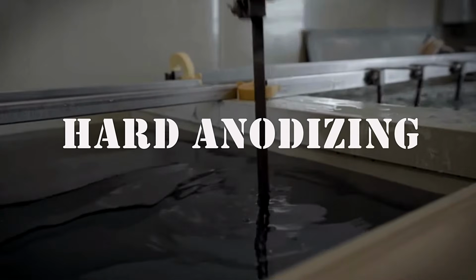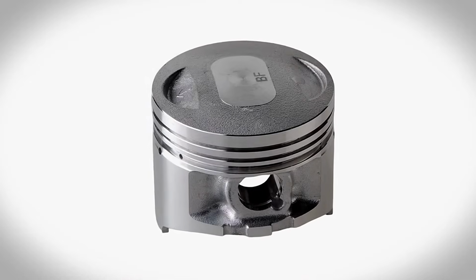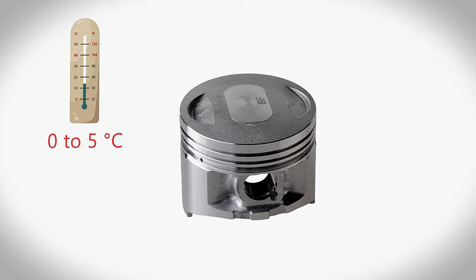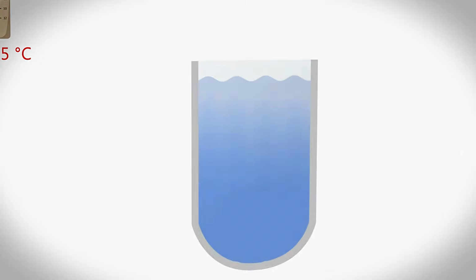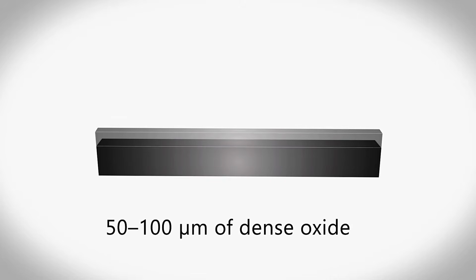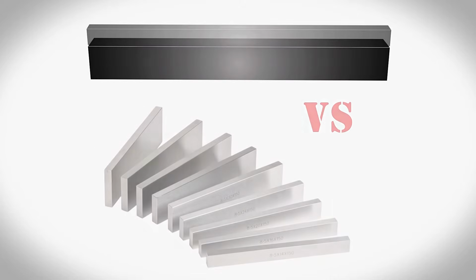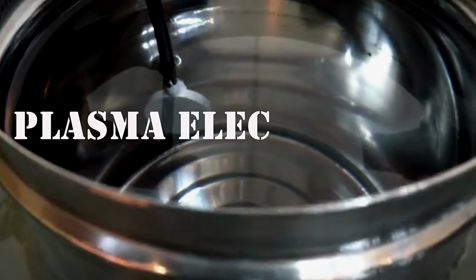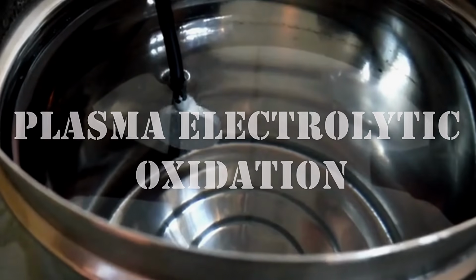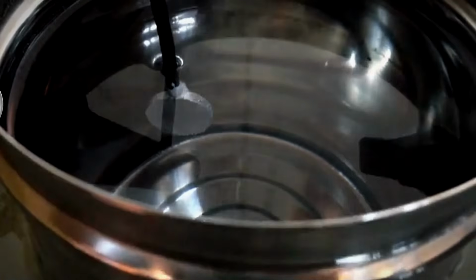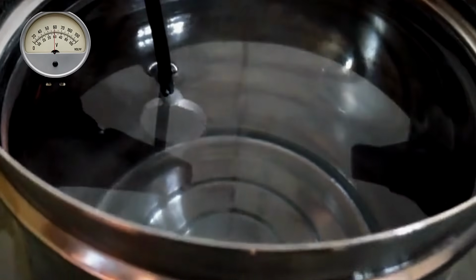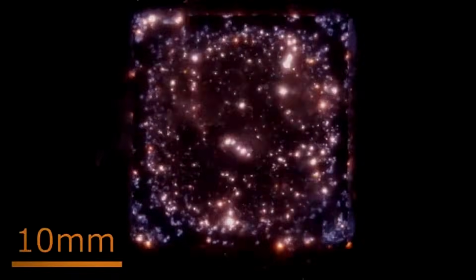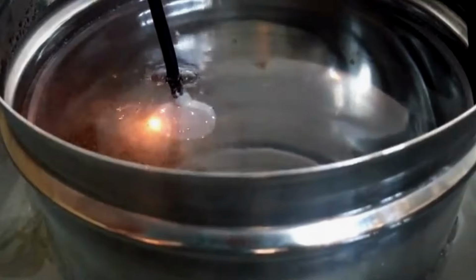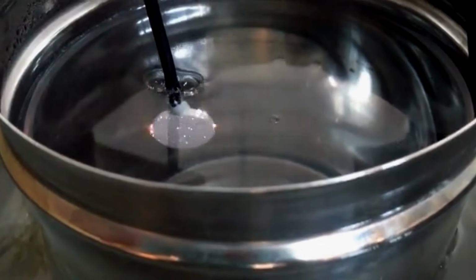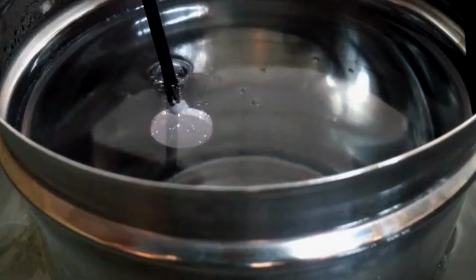For hard anodizing, used on pistons or bike parts, the bath runs colder, 0 to 5 degrees Celsius, often with more acid and higher current. You can grow 50 to 100 micrometers of dense oxide, hard enough to rival hardened steel. Then there's plasma electrolytic oxidation, sometimes called micro-arc oxidation. Now the voltage jumps to hundreds of volts. Tiny sparks dance over the surface, locally melting and re-solidifying the oxide into ultra-hard ceramic-rich layers.